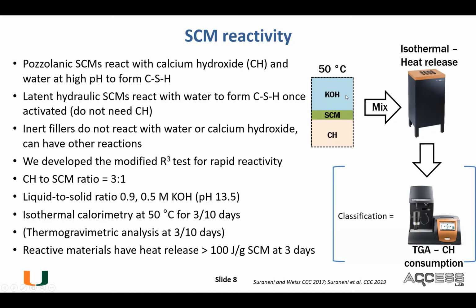But anyway, concrete has very, very high pH. At pH 13.5, silicate glasses will dissolve - that's the idea. So these pozzolanic SCMs, that's the first class of SCMs. They react with calcium hydroxide. Largely, they're low calcium materials. At high pH, they react with calcium hydroxide, and then they form CSH.